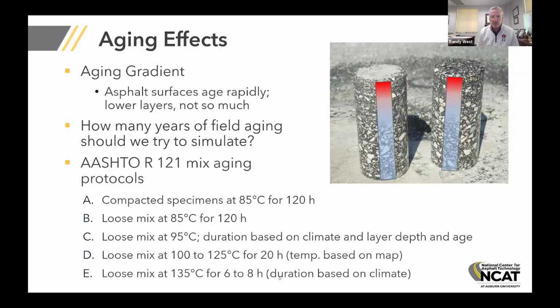And that question comes into the decision about the mix aging protocols. So currently there is an AASHTO standard. It's R121 on mix aging, long-term aging. And there's 5 choices that have all been used and maybe are currently used by different organizations, different states, and different researchers around the country. And there's ongoing work to help us still answer the question of what is the best aging or the most appropriate aging. And there may be more than one choice, but we do have these choices of different aging conditions that we can use. The aging procedure that NCAT has worked on mostly, and I'll talk about in this webinar, is loose mix aging at 135 for 6 to 8 hours. The duration, whether it's 6 hours or 8 hours, depends upon whether it's a southern climate or a northern climate.